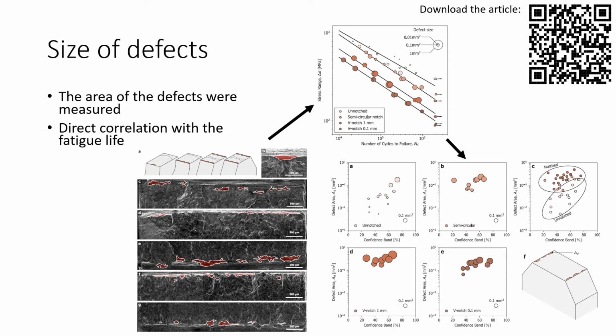So we did a further analysis of these defects, and we captured all the fracture surfaces and measured the defects as good as we could. I mean, of course, it's a bit difficult when the surfaces are not completely straight, but we measured the defects, and in the upper plot the defect size is reflected in the marker size, and then in the lower right figure the defect size is plotted versus the position within the confidence bands. So we see that for short fatigue life we have large defects, and for long fatigue life we have small defects, and this trend is strongest for the unnotched specimens.